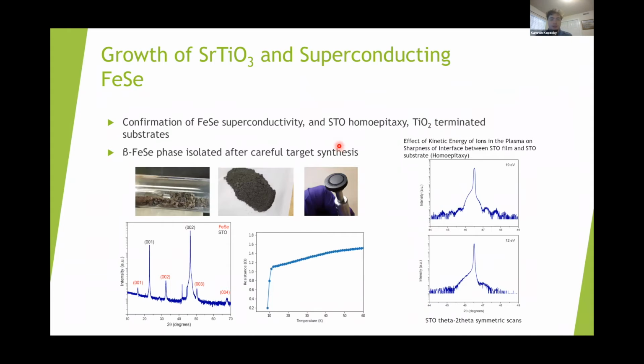So from there, we set out to show the epitaxial growth of superconducting iron selenide and the growth of homoepitaxial strontium titanate. From the theta to theta symmetric scan down here from our X-ray diffraction, we can see epitaxial iron selenide growth, C-axis oriented, as well as strontium titanate growth with respect to these substrate peaks, which is also C-axis oriented. And a bulk iron selenide film was shown to have a superconducting phase, as seen by the critical onset here on this resistance graph.